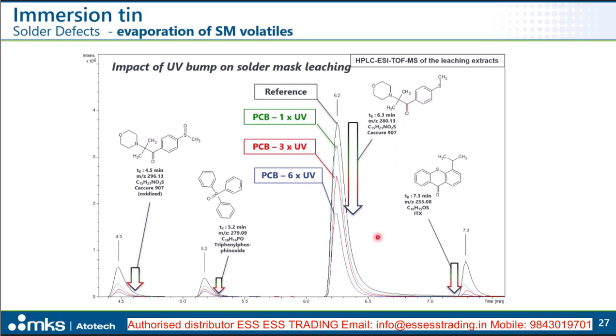And what you can see here in this graph is an HPLC-ESI-TOF-MS analysis of a solder mask leach out after different curing conditions. So you see the reference lines in black, and then we have applied different UV bumps or UV cycles to cure the solder mask. And what you can see is that you can reduce the leach out of the marker components by applying UV bumping. So meaning there is a chance to improve the solder mask properties or conditions, or to make the solder mask more resistant towards the immersion tin process by additional UV treatment.